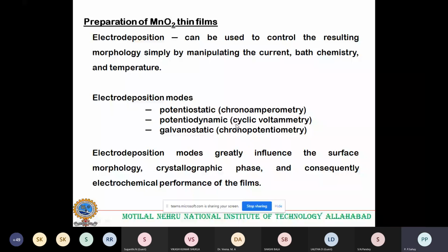And in my case, I have observed that these three different modes influence the surface morphology, and because of the surface morphology, the crystallographic phase, and consequently the electrochemical performance of the film. In our case, the crystallographic phase was the same in all the cases, that is epsilon MnO2, the hexagonal crystallographic phase. But so far as the morphology is concerned, the electrochemical performance of the film changed.